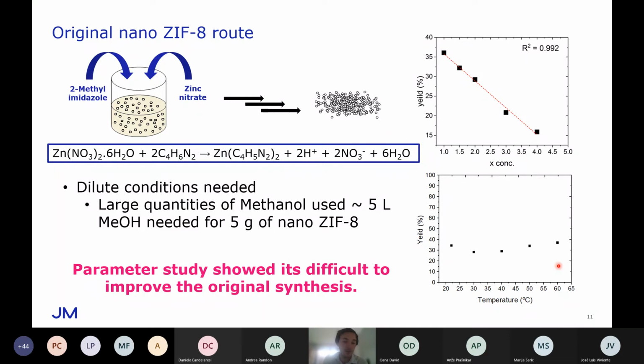Now, this is inherently due to the chemistry that's going on within the reaction. If we increase the concentration of the reaction, not only are we going to increase the concentration of our desired products, we're also going to increase the concentration of our undesired products, namely nitric acid. When the nitric acid is formed, the pH regime changes, and ZIF-8 is not stable under acidic conditions, so it doesn't form or redissolves into the solution. So really, there was no option for us to intensify this reaction ourselves. We needed to find an alternative route to make large quantities of this nano-ZIF-8.